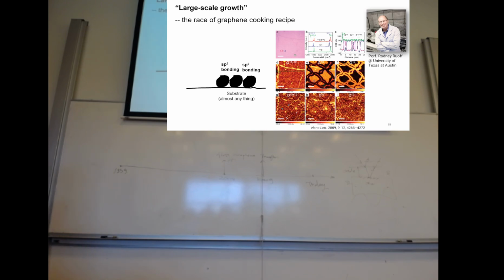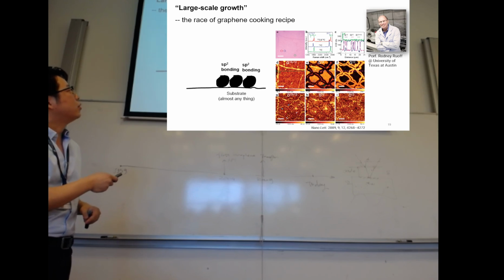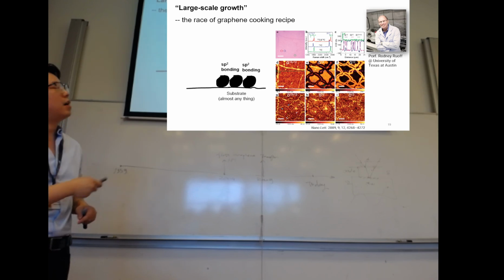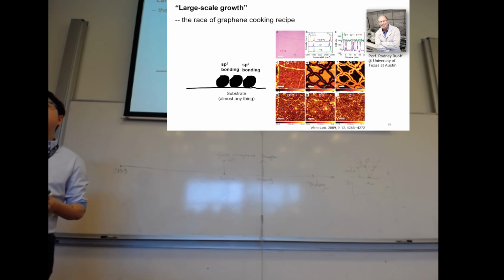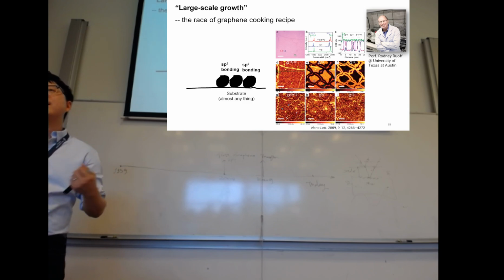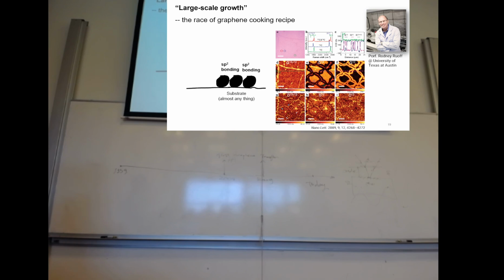And then there's also a famous experiment from UT Austin, Professor Rodney Ruoff. He found that if we grow graphene in an alternating manner with the isotopes carbon-12 and carbon-13, you can feed a carbon precursor of carbon-12, then stop the growth, and feed another precursor with the carbon-13 isotope, so that these two materials have different Raman spectroscopy. Because the mass of the atoms is different, the phonon modes are different in terms of energy. So you can really do the mapping in real space and see how this crystal will grow.